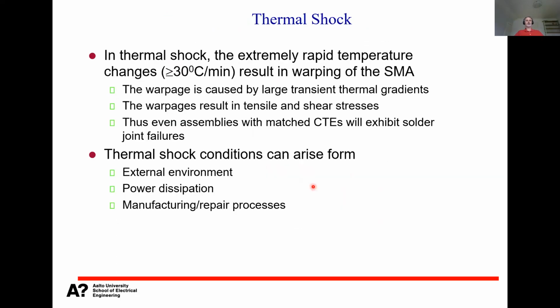So finally, I would like to conclude here. What is the basic difference between thermal cycling and shock? I already mentioned this one. When we are talking about thermal shock, it means that the temperature cannot even out inside the product when the temperature is changing very rapidly. Typically, there's a definition that when we are talking about dozens of degrees per minute, then we are talking about thermal shock. If it's smaller than that, then it's thermal cycling.